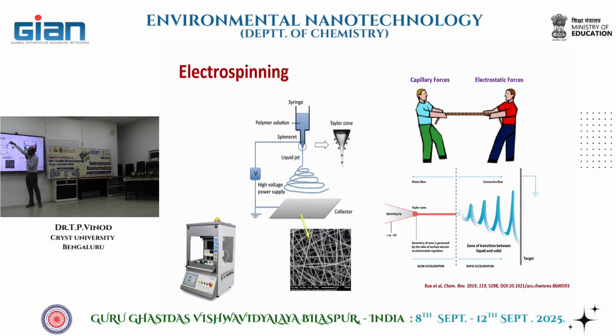And then this polymer solution is mechanically pushed down with a controlled force. Usually you use a syringe pump. A syringe pump can exert a controlled amount of force at a given time. Usually it's given by so many milliliters per minute, that is the unit of flow of this polymer. So the polymer is flowing like this, and the voltage is applied, and then you get the deposition of nanofibers.